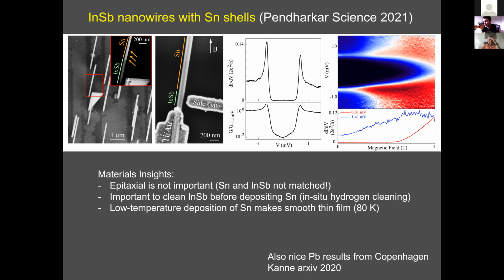But maybe the most interesting thing we learned, the most positive thing we learned from this, is that for a while people said that, look, to have clean data like this, you need a lattice match between the semiconductor and the superconductor. The atoms have to go continuously, smoothly, without defects from one to the other. And we showed in this work that this is not the case. Tin is not lattice matched with indium antimonide in this form, this beta tin. It has grains that are oriented all different ways. So there is no epitaxy, it's called, in this material. But what we found important is that the interface between indium antimonide and tin needs to be cleaned very well and very gently. So we use this hydrogen cleaning to remove the interface oxide and deposit the superconductor.